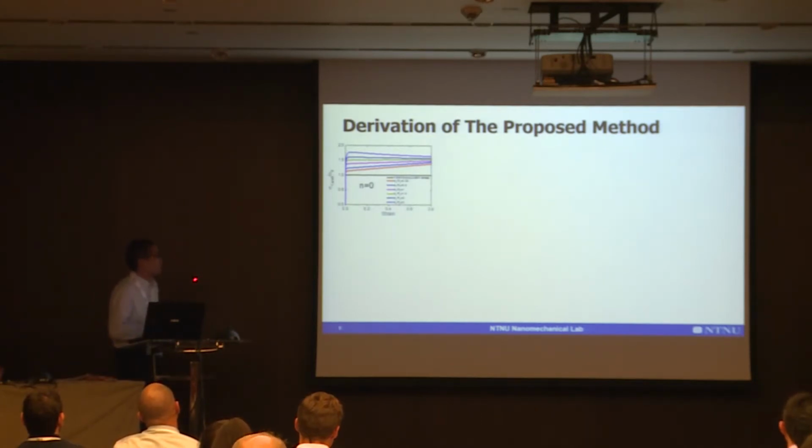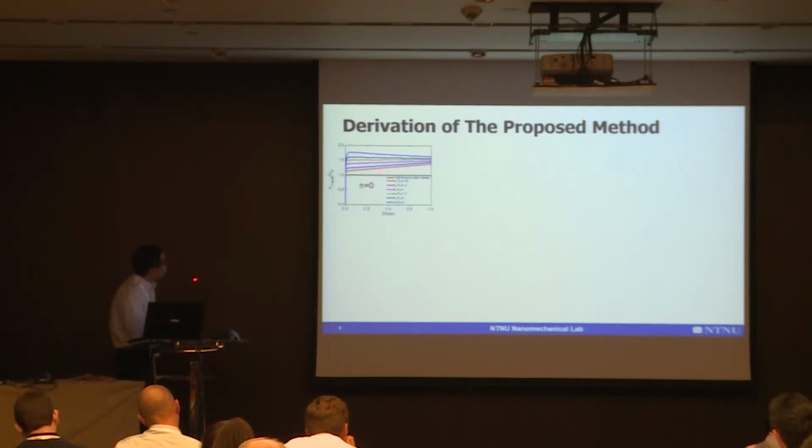And from the numerical analysis, we obtained the true stress strain from the notched specimen. Here in this figure, I presented the results for the perfectly plastic material. We can see the true stress here from the notched specimen is normalized by the yield stress. And we can see that for these true stress strain curves, for the notched specimen with the ratio of A0 over R0 smaller than 2, the stress goes up. The true stress goes up with the increase of strain.